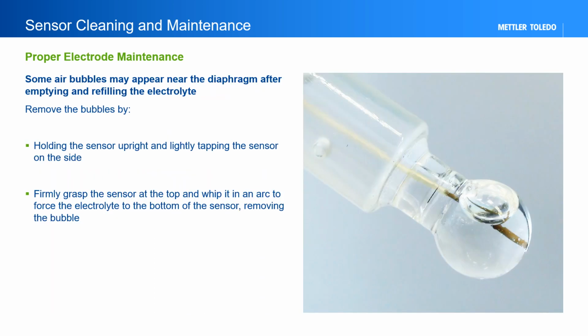When emptying and refilling the reference electrolyte, one may introduce air bubbles into the tip bulb. Air bubbles can be removed by holding the electrode upright and lightly tapping the side until all the air bubbles rise to the head of the electrode.